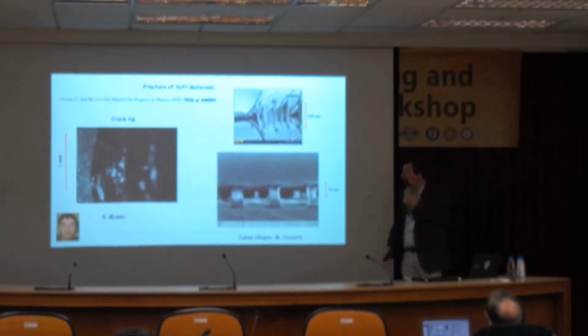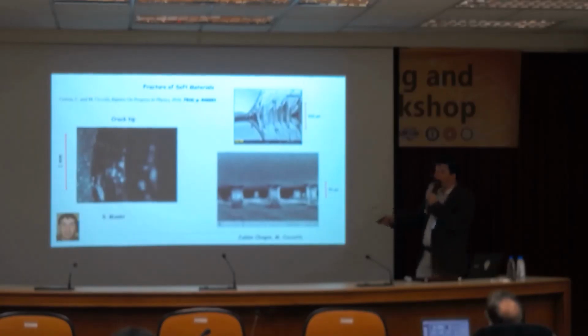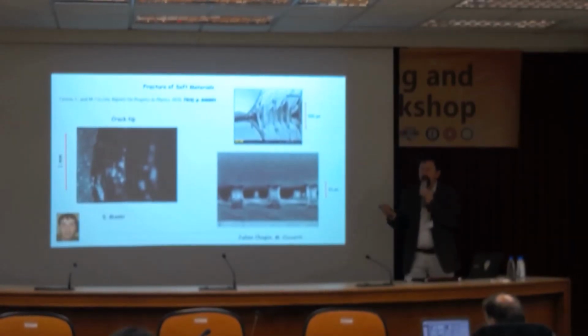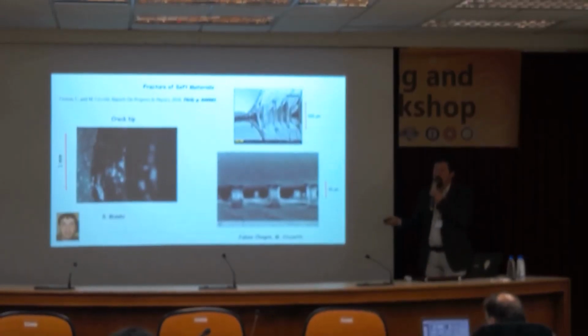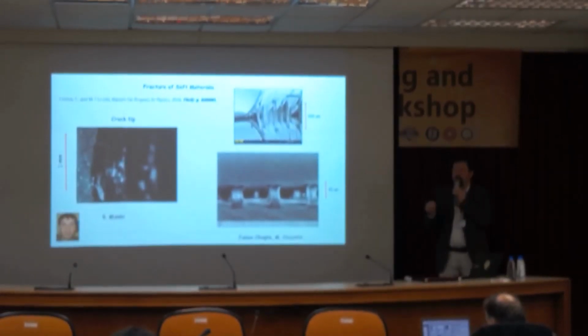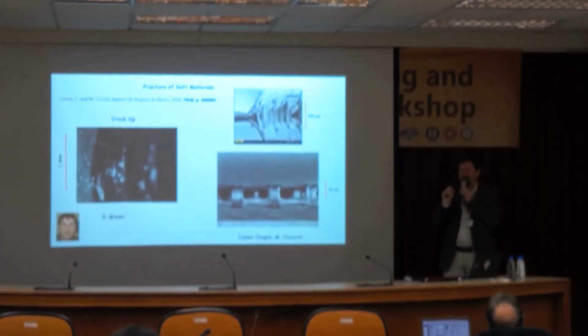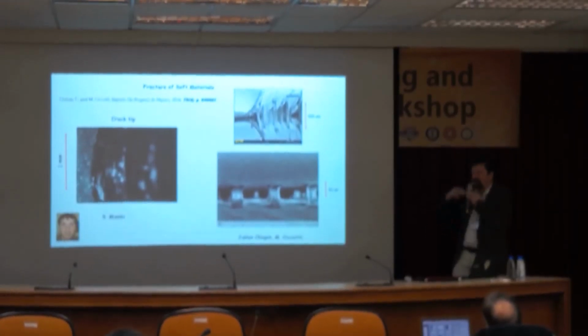Yes? It looks more like a, it's absolutely, it's a crack, it's a surface. Well, it's a question of radius. Basically, if you're thinking of the previous glass, the radius is a few nanometers. This is going to be typically hundreds of microns. So there is no essential difference, but the radius is very different. And so the locus of bond fracture will be much larger. The main difference is that in the glass, the radius is similar to the molecular scale. So somehow you can look at the problem as a molecular problem, and you're still localized there. Here, clearly, it's not possible. But otherwise, indeed, it's a surface.